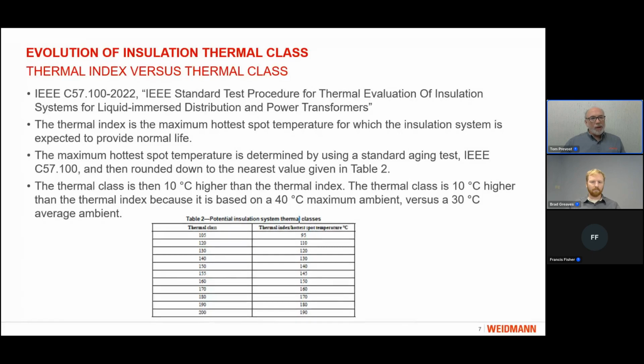And what the test program itself provides is the thermal index. So the thermal index is the maximum hottest spot temperature for which the insulation system is expected to provide normal life. If you remember the previous slide, the thermal index for a 65 degrees C rise transformer, for example, is 110 degrees. So when we're looking at an aging test, the maximum hotspot temperature is determined by using the aging test and then rounding down to the nearest value given in this table, which I excerpted from the standard.